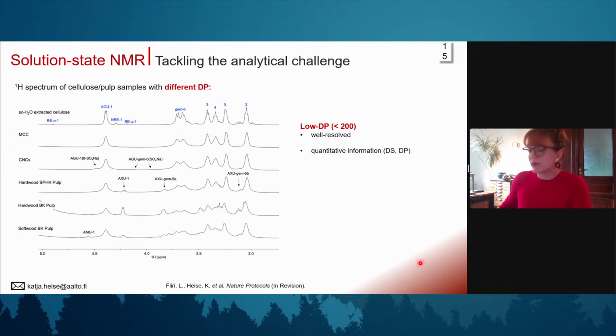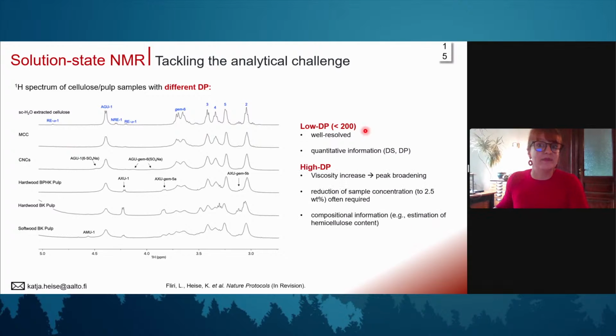But if you have, for example, high molecular weight or high DP samples, you have a viscosity increase, so sometimes it's difficult to actually handle your samples. You observe peak broadening, so it might be necessary to reduce the amount of cellulose in your sample to 2.5 weight%, which is still possible. Then you get reasonable spectra, but you lose the full resolution of your signals, so the quantitative information. But you can still estimate, for example, compositional information, like hemicellulose contents. So it's widely applicable also to pulps, and not even only to pure celluloses.